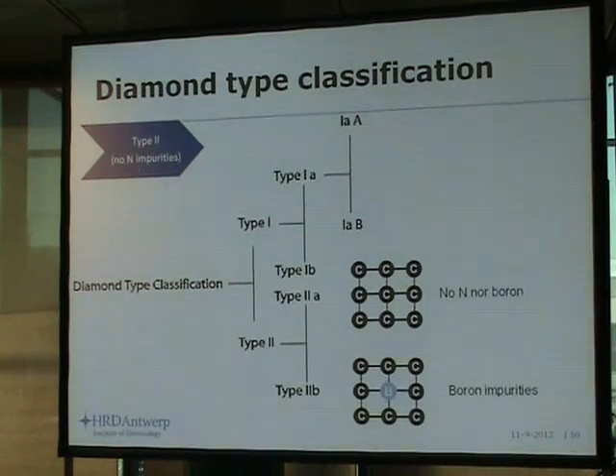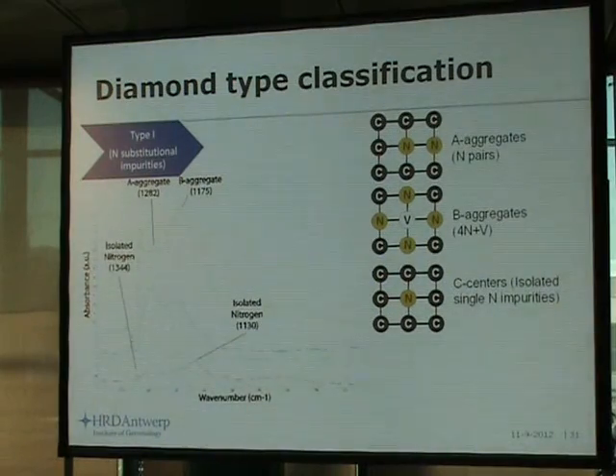If you don't have any nitrogen, it's called type 2, or type 2b when it's containing boron. Type 2a diamonds are the most pure diamonds one can find in nature or can be produced in an industrial reactor. Why is that important? I come back to that later on. So how can you make the distinction between those types? It's just by looking at a certain region in the infrared spectroscopy spectra, and then you get different typical features.